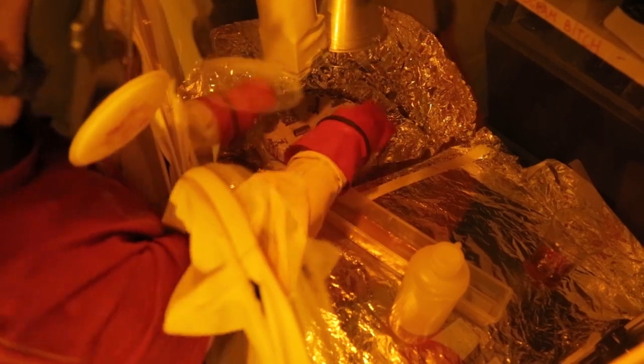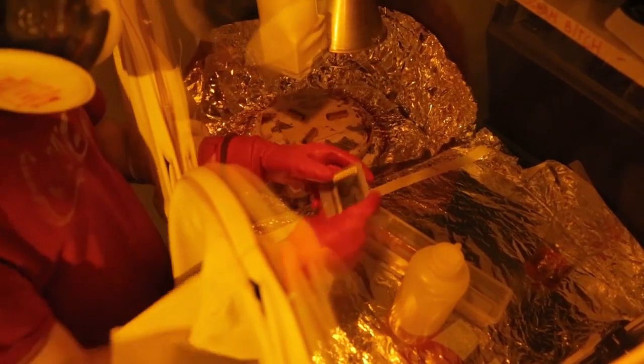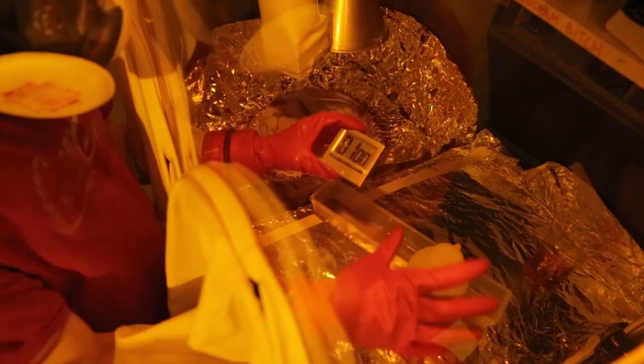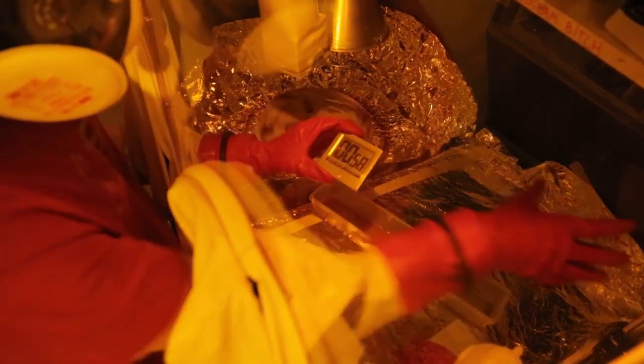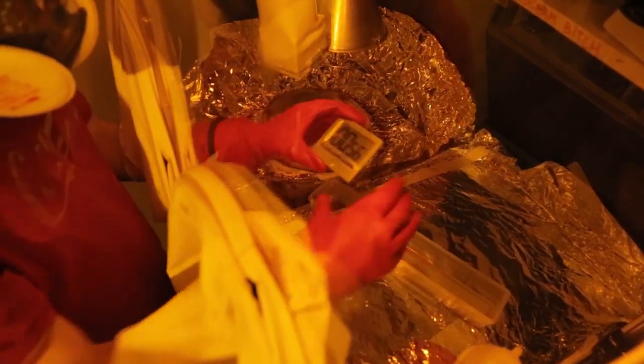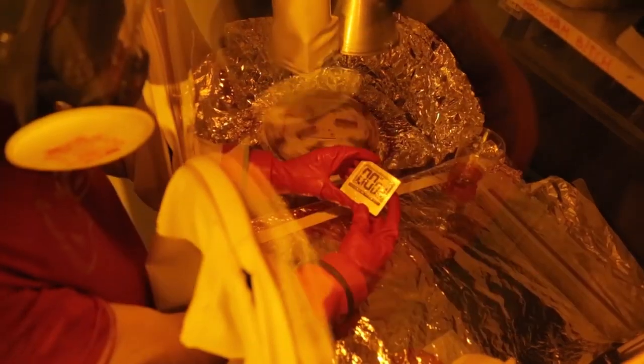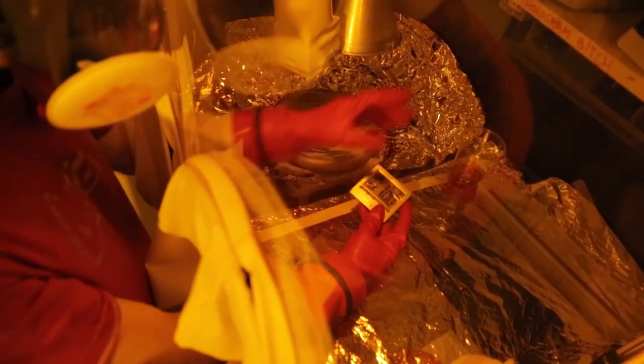Once the plate is completely covered, I place it on the spin coater. It's an old record player, spinning at 80 rounds per minute. While spinning, the plate rests on 3 spacers made from a cut garden hose. The centrifugal forces will even out the gelatin.